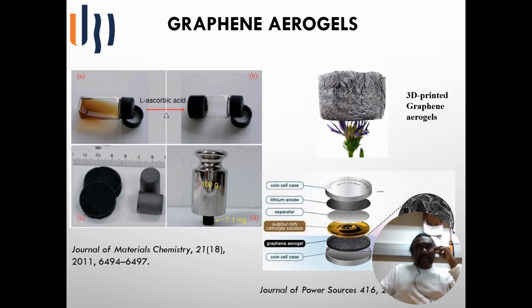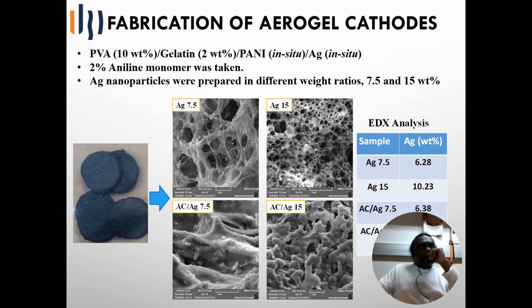These are some reported graphene-based aerogels, as you can see here. You can see the strength of a graphene aerogel, and also in the image a 3D printed graphene aerogel. And here you can see the graphene aerogel used as an electrode in lithium coin cells. We have developed aerogels based on polyvinyl alcohol, gelatin, and polyaniline with silver nanoparticles. Here, the polyaniline and silver nanoparticles we prepared in situ, and then we cross-linked PVA and gelatin with glutaraldehyde solution, and after gel formation, it was freeze-dried using a lyophilizer.